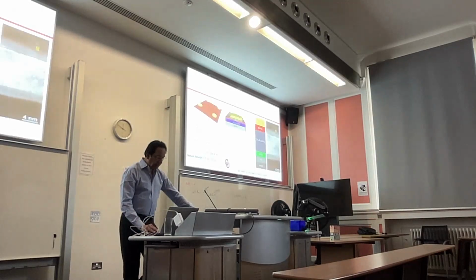A ferroelectric tunnel junction basically consists of a bottom electrode, then a ferroelectric layer, and then a top metallization. For example, there's a top metal like chromium gold here, and there is barium titanate, which is a ferroelectric layer, and the aim of these experiments was to insert some magnetic materials here, like LSMO, which is a ferromagnet. Then the bottom electrodes are conducting layers underneath. If you look at the transport property of this capacitor, you get the resistance versus applied voltage. You get this very nice hysteresis curve. And you can see that the on ratio to the off ratio is, this is really the higher conductivity. This should really be on and this should be off.